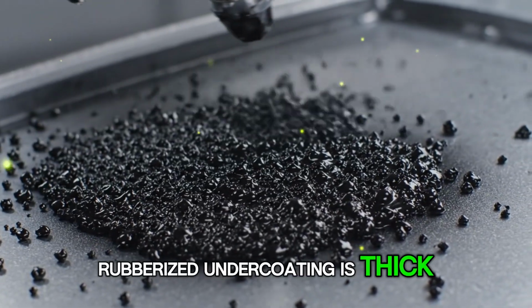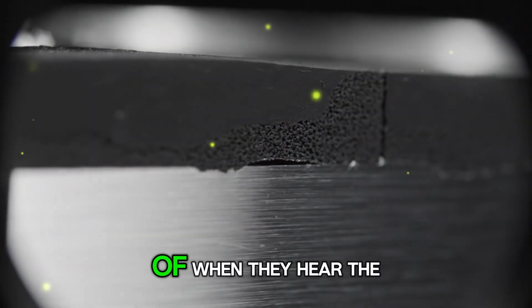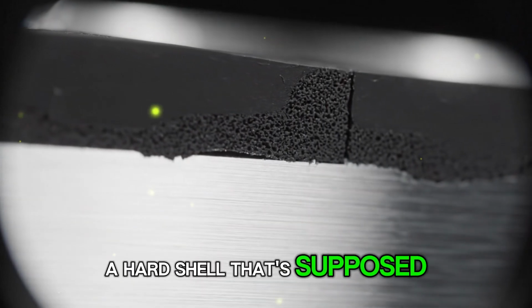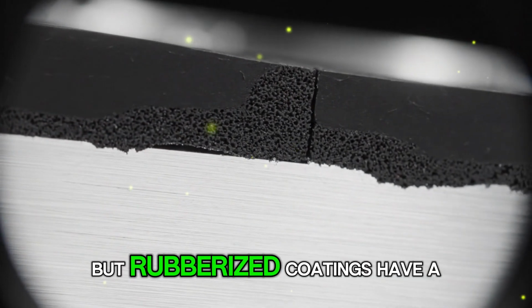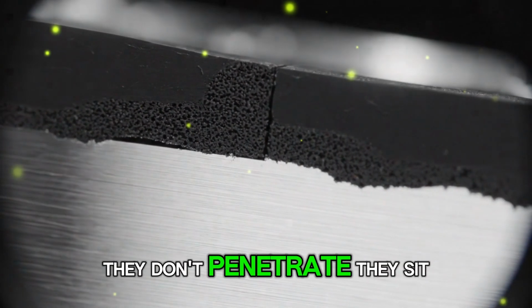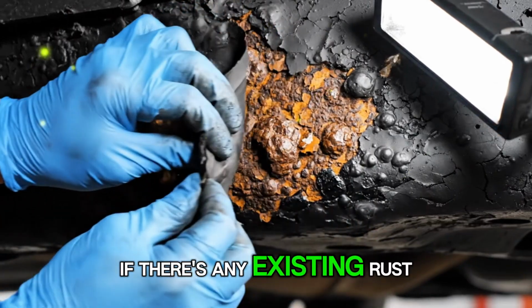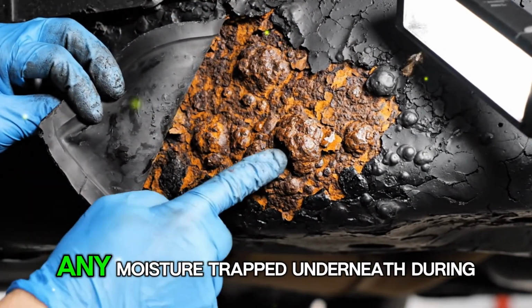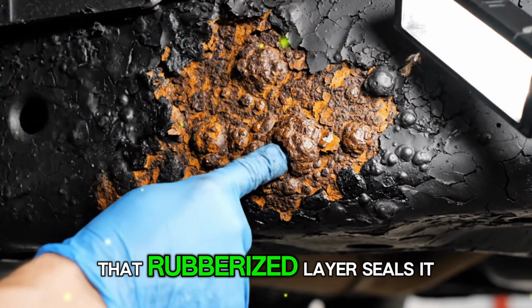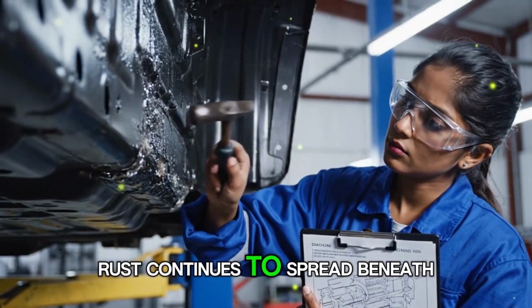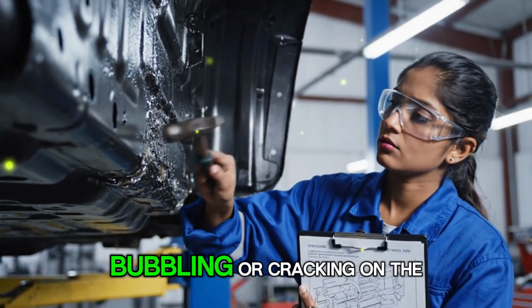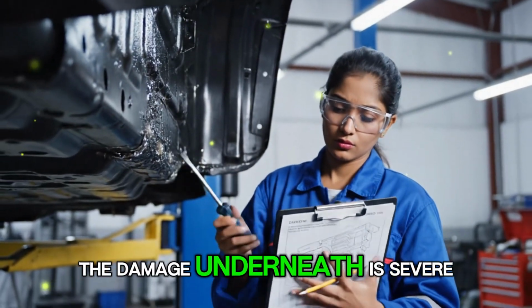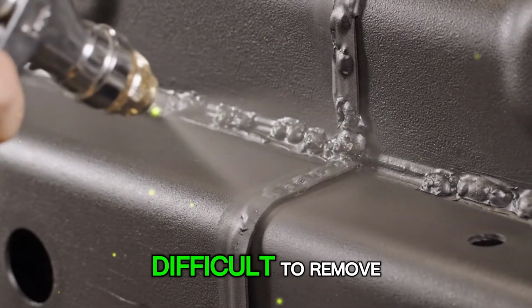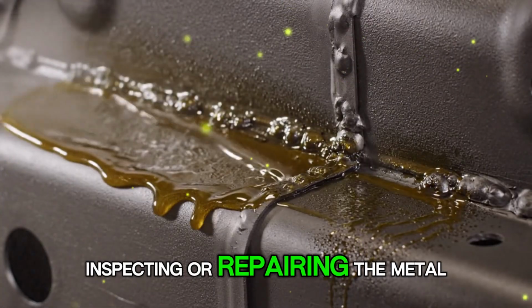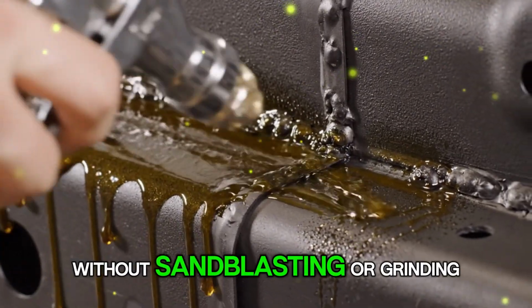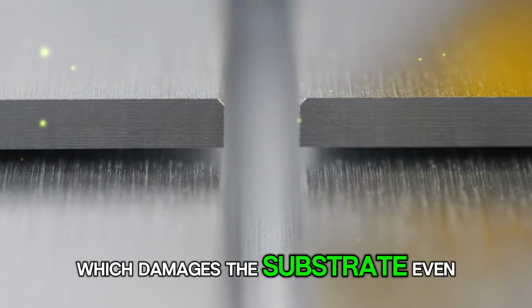Rubberized undercoating is thick, black, and permanent. It's what most people think of when they hear the term. It creates a hard shell that's supposed to block moisture and road debris, but rubberized coatings have a fatal flaw. They don't penetrate, they sit on top of the metal. If there's any existing rust, any surface contamination, any moisture trapped underneath during application, that rubberized layer seals it in. Rust continues to spread beneath the coating. By the time you see bubbling or cracking on the surface, the damage underneath is severe. And because rubberized coatings are difficult to remove, inspecting or repairing the metal becomes nearly impossible without sandblasting or grinding, which damages the substrate even further.